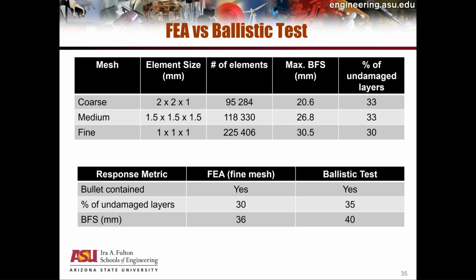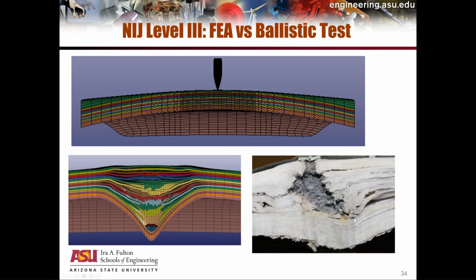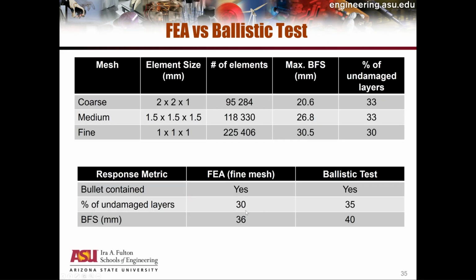Our prediction showed that we could capture the bullet, get a number of undamaged layers, and get a back face signature of roughly 36 millimeters when we looked at all 6 shots, and the ballistic test showed that the actual back face signature was 40 millimeters. The undamaged layers were 35% in the test. If you go back and look at the previous slide, these are the layers that are undamaged, and the computer model says that 30% of the layers were undamaged. So again, reasonably close to what the actual test results showed.